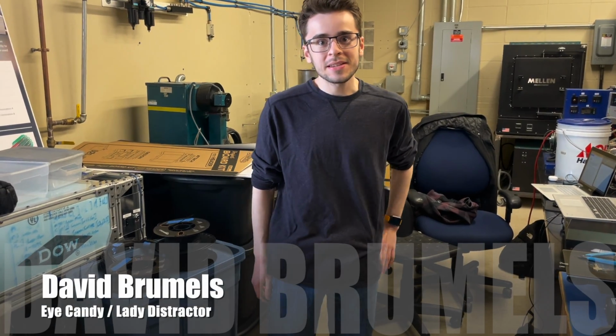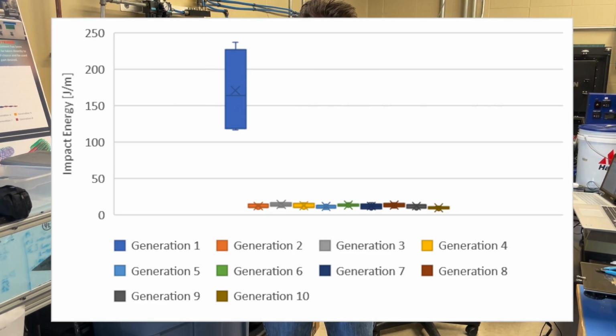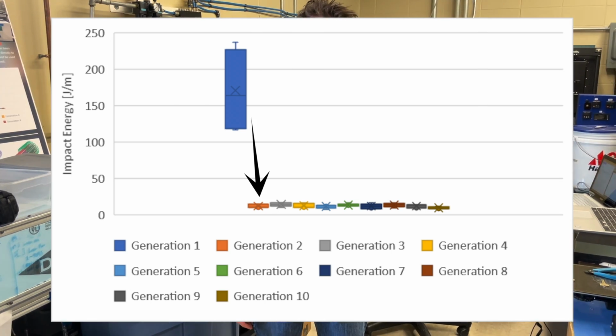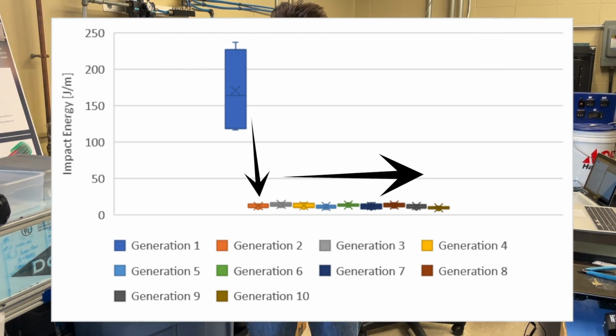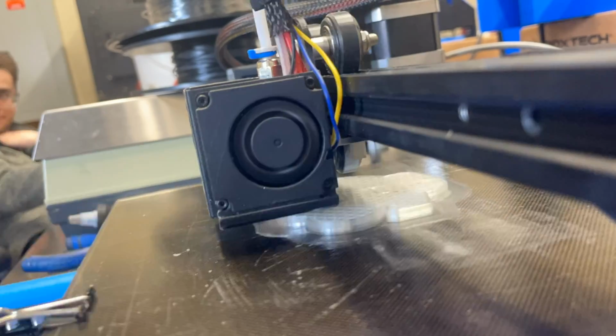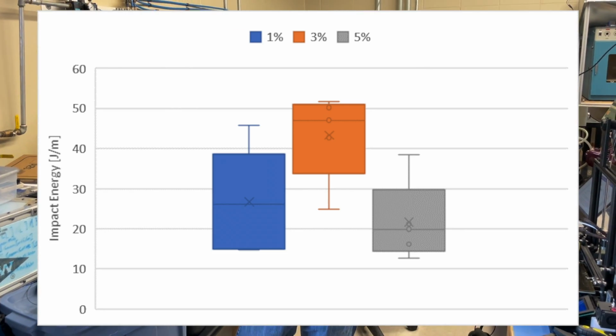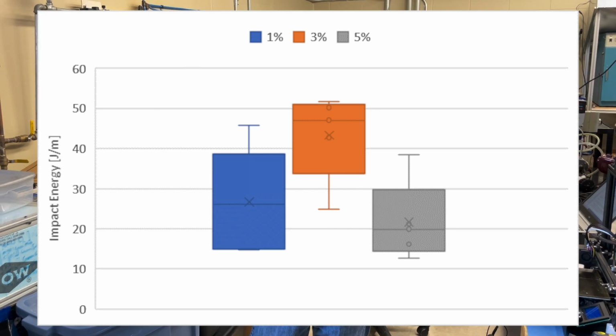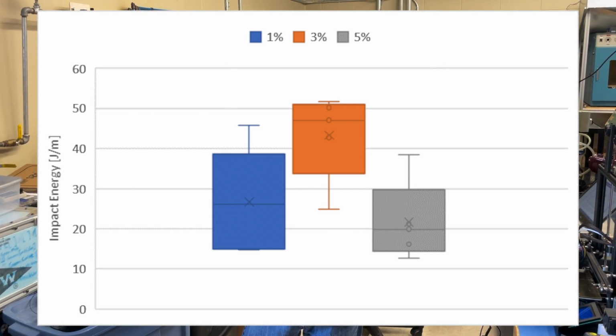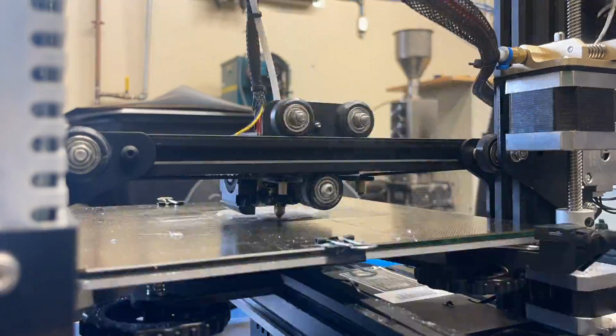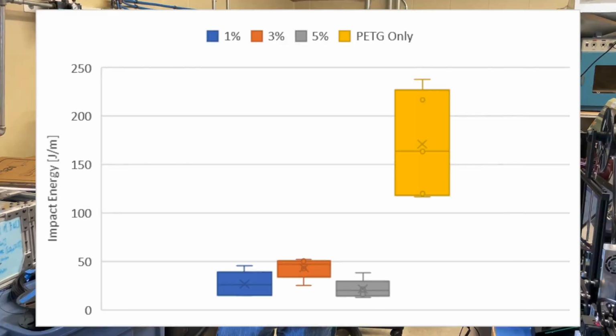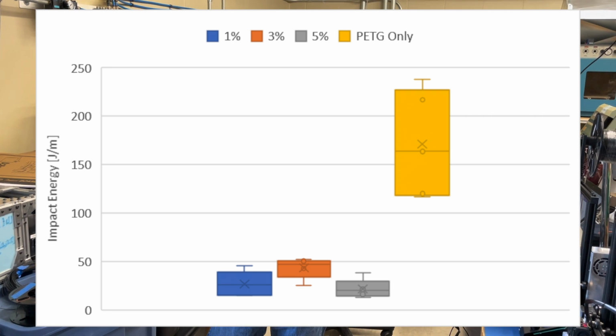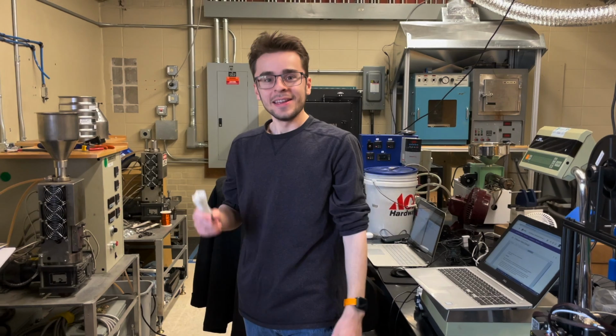On the testing side of things, impact testing revealed that there was significant material degradation from generations 1 to 2, however, there was minimal degradation from generations 2 through 10. The carbon nanotube impact testing revealed that 3% performed the best and 5% performed the worst, due to the material becoming increasingly brittle as more carbon nanotubes were added. Additionally, thermal testing of the carbon nanotube composite revealed that thermal conductivity doubled in just the 1% mixture compared to pure PETG. Isn't that cool? That's pretty awesome.